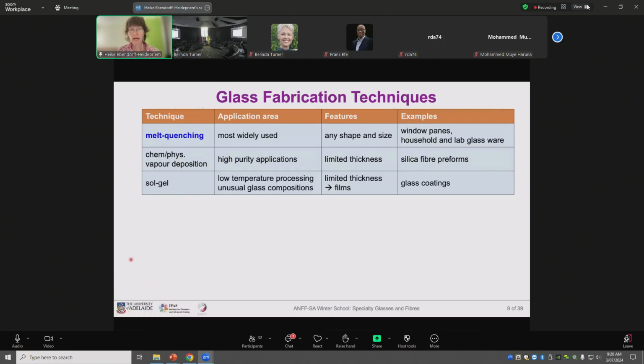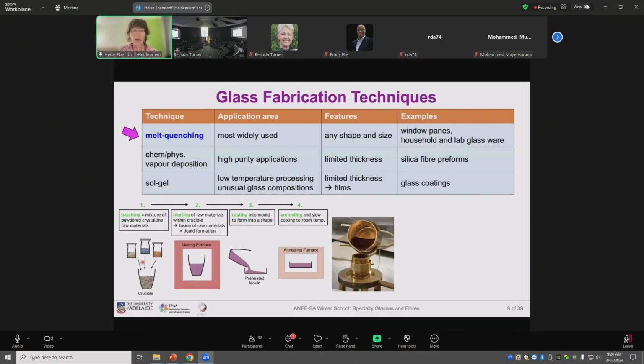Okay, now I talked about composition, I talked about properties, now a few slides on glass fabrication techniques. The most widely used technique is the so-called melting quenching technique. This technique is used to make window panes, household and labware glasses. And so it works as follows. First, a mixture of crystalline raw materials is made according to the required glass composition. This mixture is placed in a crucible.